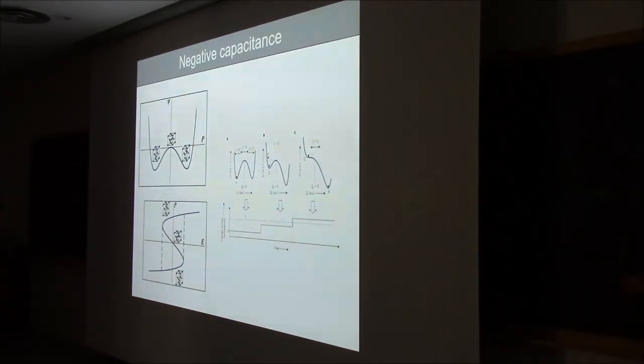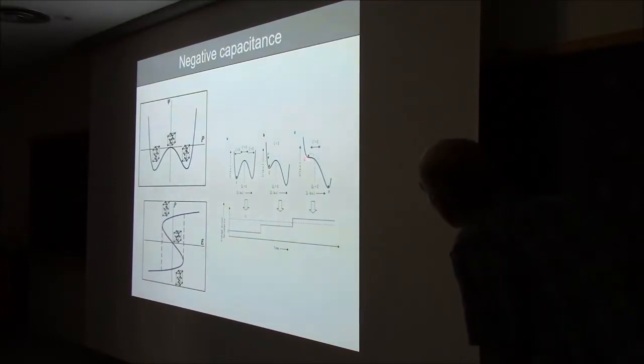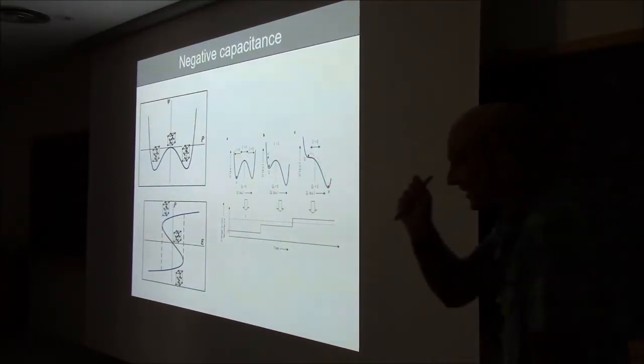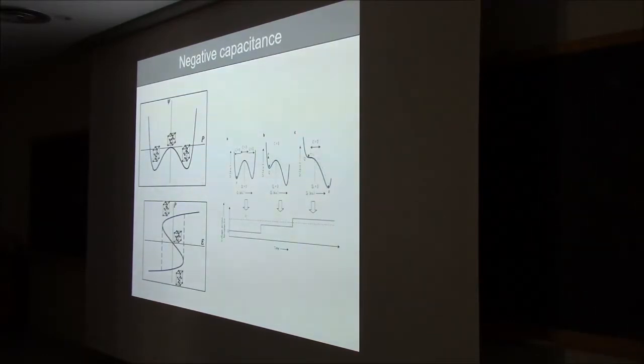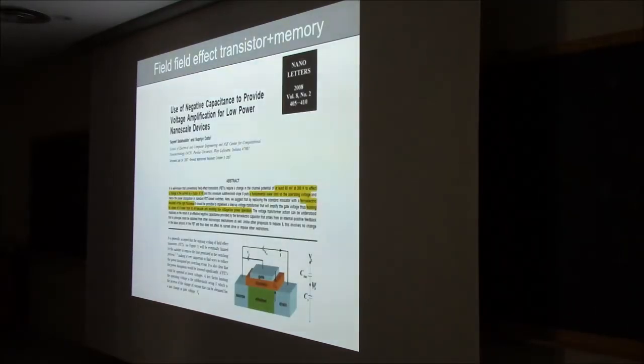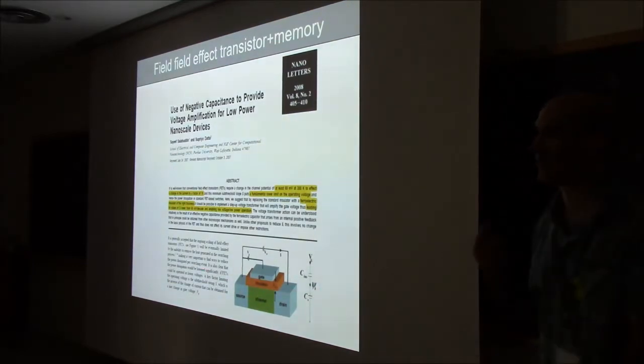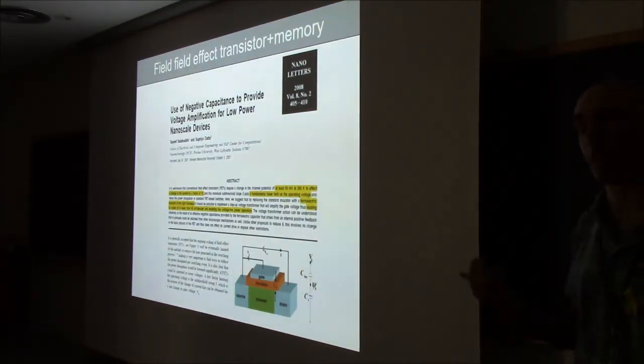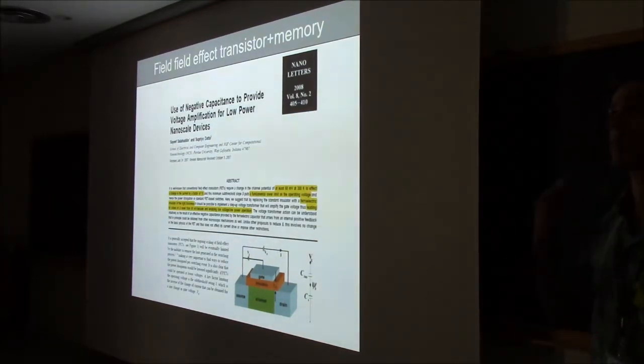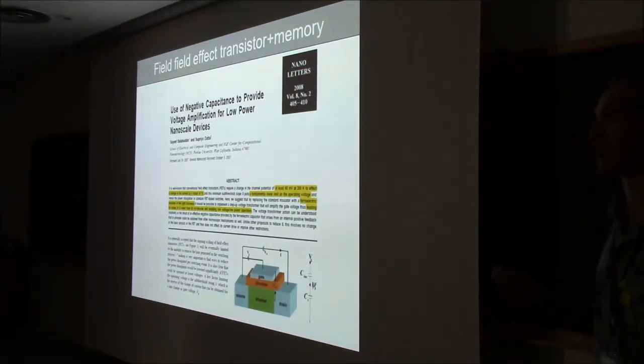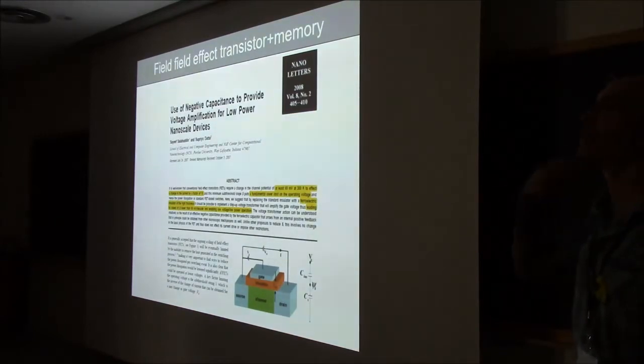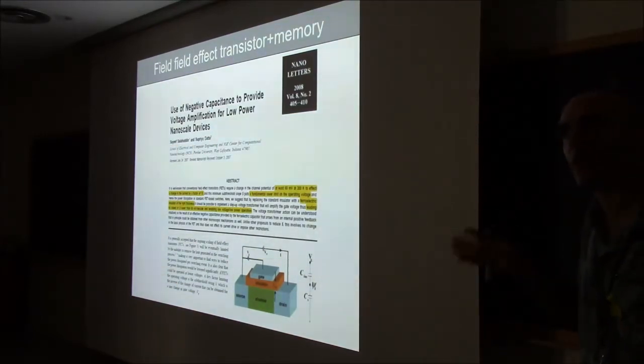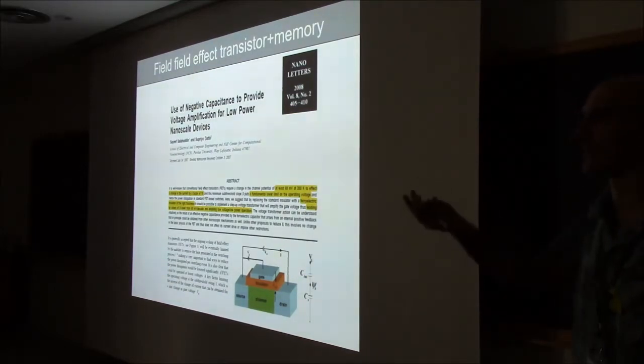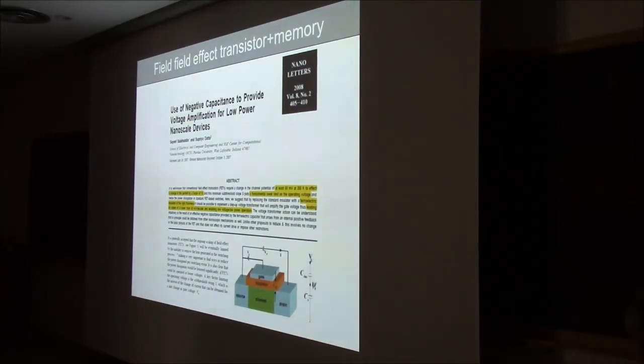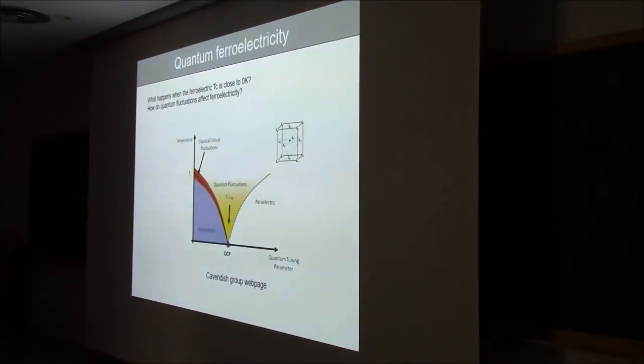Why is this useful? Well, it's useful because when you're just on the cusp of going from the plus polarization to the minus polarization, any small voltage is going to give you a ginormous polar response that you can then use to modulate the conductivity of a channel. So people who know about transistors, and I'm not one of them, believe that you can use this negative capacitance effect to achieve higher performing transistors. Transistors where you can get a much bigger gain than you would get by normal semiconductor processes. You can overcome what's called the Boltzmann tyranny. Okay, that's it.